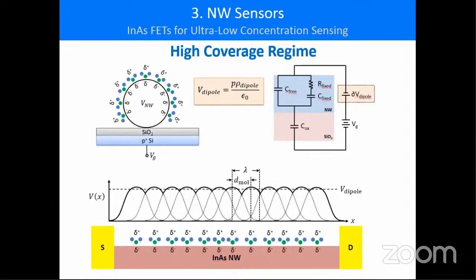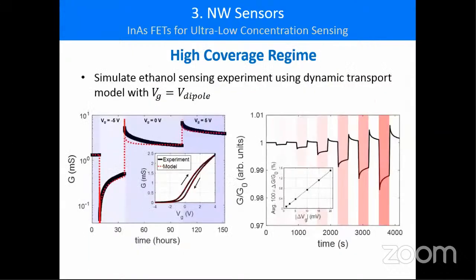So how did we account for this additional dipole bias? What we did was we just assumed it's like another back gate. And if we do that, then with that model we can simulate the additional gating potential. And you can see the dashed curves on the left figure as completely capturing the key aspects of the dynamics, and also the steady state on the right that we discussed.